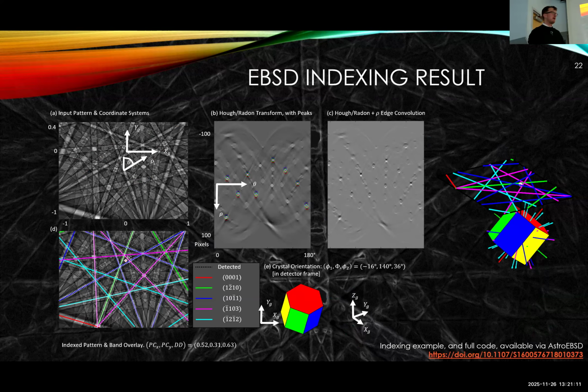If you are interested in the nerdery, we published a fully open source algorithm for this, because for a while there weren't any out there. It's called Astro EBSD. You can get some MATLAB code and it will talk you through it. But effectively, here's the raw pattern. Here's a Hough transform. Here's the peak identification step. And then once you've done that, you work out the bands, you work out the orientation, and you then can relate the crystal pattern to the crystal itself. And that's what you do at every single point in your map.